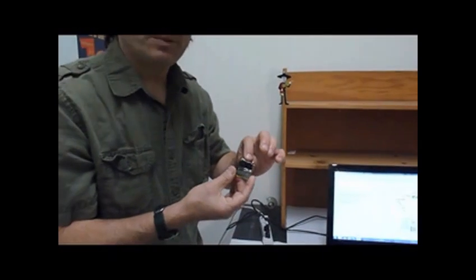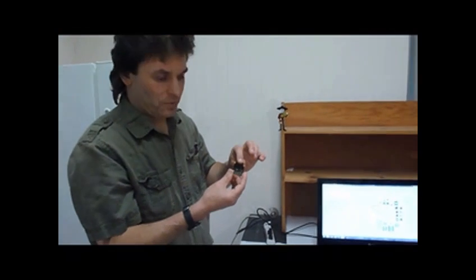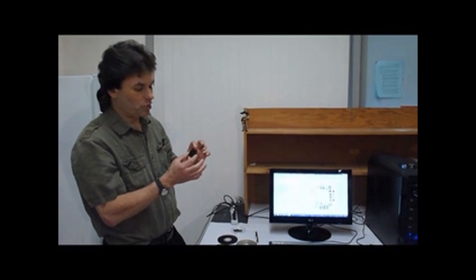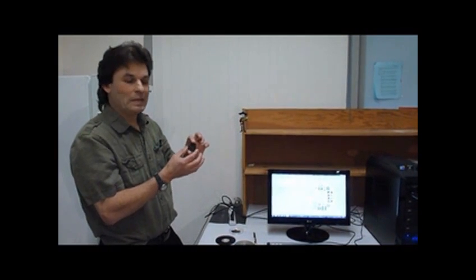What's nice about this material, unlike conventional supercapacitors, which can be charged and discharged quickly but don't store much energy, is that this stores as much energy as a conventional battery. Yet it can be discharged or charged 100 to 1,000 times faster than an ordinary battery. So for example, charging this up for 2 seconds, we can run a light-emitting diode for 5 minutes or so.